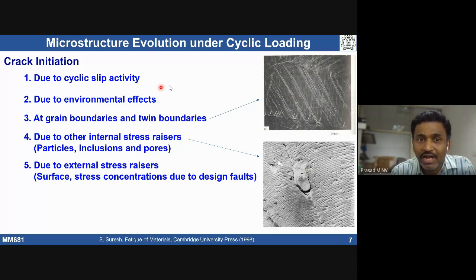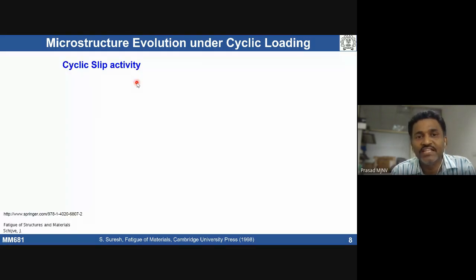But what I'm talking about under cyclic loading conditions, we do see cyclic slip activity. The slip activity can lead to formation of internal stress risers. What is the meaning of cyclic slip activity? Assume that at a certain location we may see some stress concentration is going to develop. So how is it going to develop?